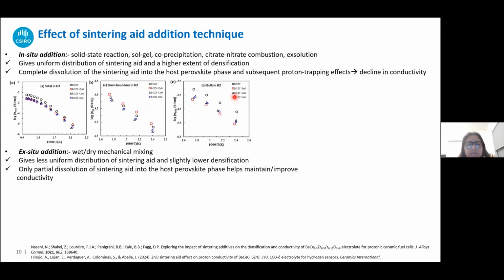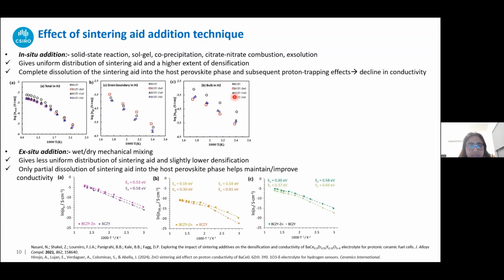However, in comparison, when we have the ex situ addition, which is basically where you first prepare your BCZY and then add your sintering aid either through wet milling or dry milling, this obviously gives a less uniform distribution, leading to a little less densification. However, there is only partial dissolution of the sintering aid, and this helps to maintain or in some cases even improve the conductivity. So this is one example where you can see that they have used BCZY and the zinc sintering aid as well. In the case of the zinc sintering aid, they have seen an improvement in the conductivity.